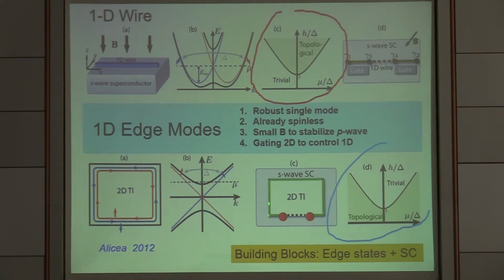So the device is designed such that you have a 2D topological insulator, and you have edge states going around. Then you want to cut this edge state by gapping out the edge state. One way to do it is to put a ferromagnetic insulator on these 2 points. Therefore, a pair of Majorana boundary states can be localized here. Okay, so basically from this cartoon you can see that we need an edge state. Then you need a proximity effect, also the proximity effect from the ferromagnetic insulator. So you need 3 ingredients.